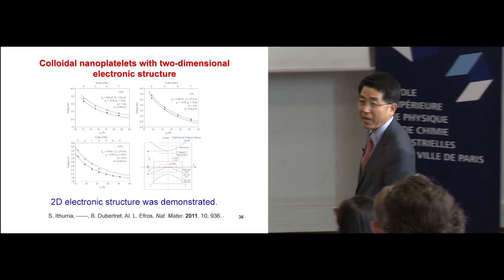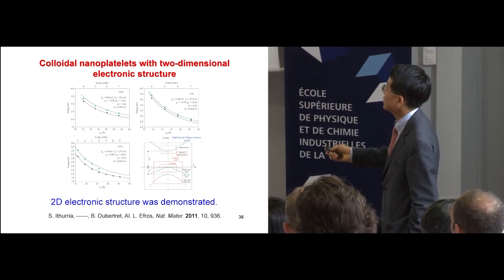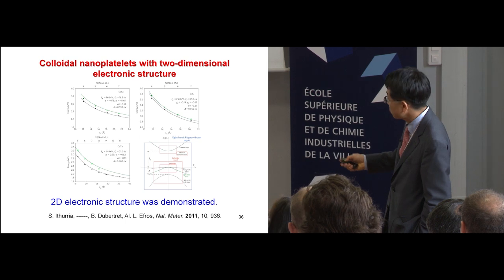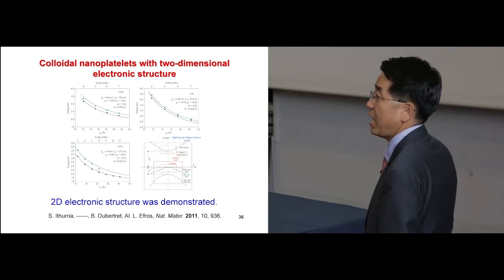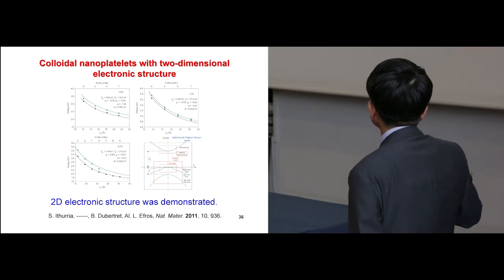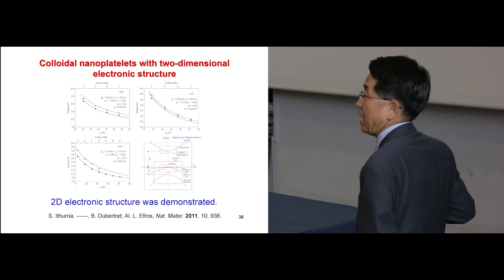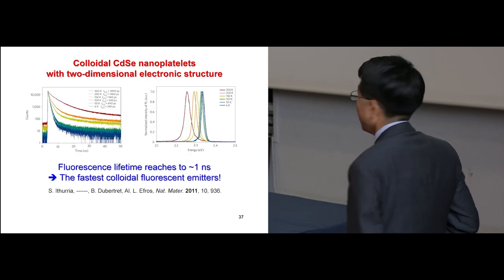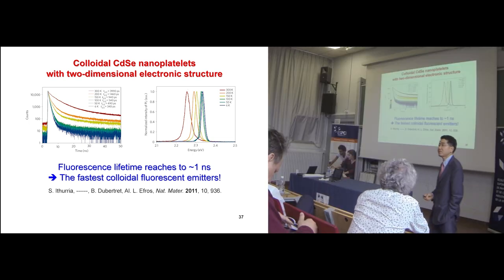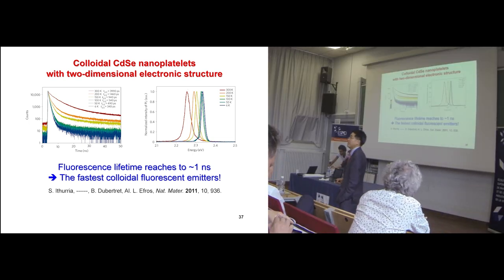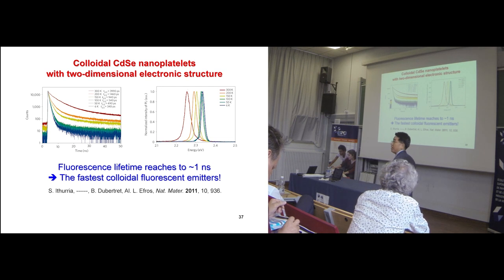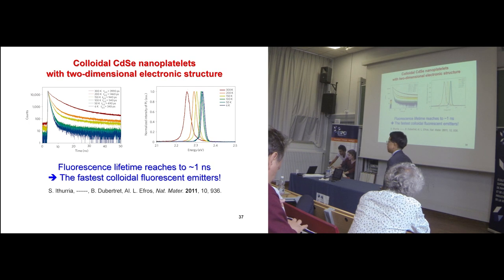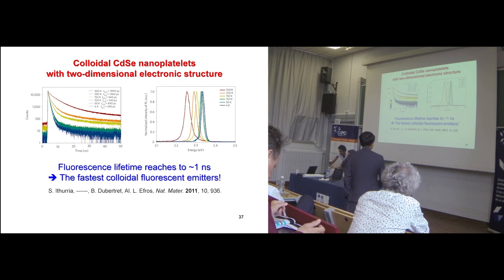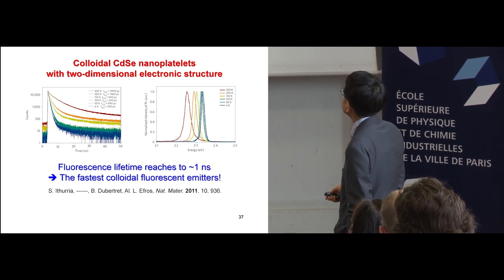By combining experimental optical spectroscopic results and calculations, they demonstrated that the 2D quantum structure is actually working. On top of that, they also measured the fluorescence lifetime, and it turned out to be on the nanosecond scale. It's very short, and this is probably the fastest quantum fluorescence lifetime ever reported. This is what they reported in Nature Materials a couple of years ago.